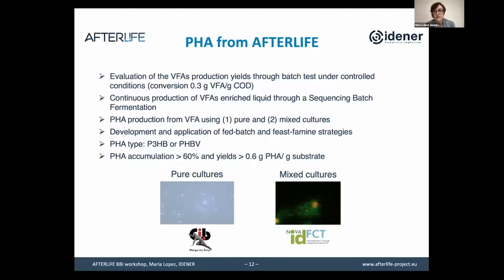Depending on the selected pathway for the production, we have developed fed-batch strategies in the case of the pure culture to increase the PHA accumulation, or feast-famine strategies in the case of mixed culture. In both cases, we have produced PHA mainly of two types, the P3HB or the PHBV. Also in both pathways, we have accumulation higher than 60% of PHA and yields higher than 0.6 grams of PHA per gram of substrate.